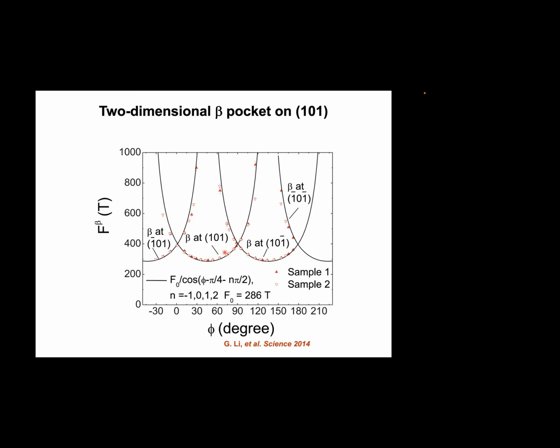Now, the only way that we can argue it is coming from the surface is the conventional wisdom, combined with having seen a very good insulator with the chemical potential exactly inside that energy gap. And combining these two, we thought we saw observations from surface states. But as experimentalists, the data itself told us that this is a cylinder-like Fermi surface. And in early days, people would just say this is a two-dimensional Fermi surface because there's no kz dependence.